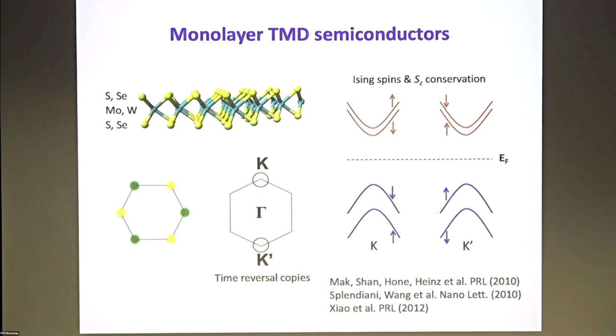This is the crystal structure. If you look from top down, it looks like a honeycomb lattice, just like graphene, except that the A and the B sublattice sites are not the same. So the inversion symmetry is broken, so that you actually open up an energy gap at the K and the K prime point of the Brillouin zone. So you can just think of it like a gapped graphene with a gap size on the order of 1 eV here.